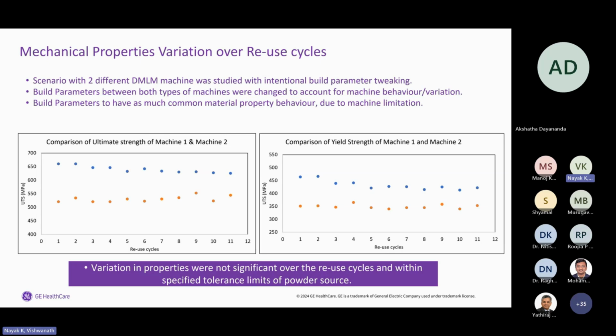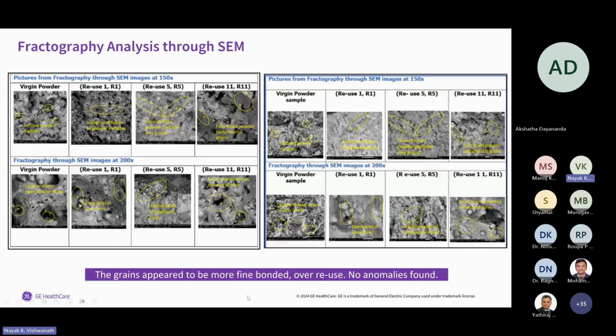So we see that variation is not significant within the reuse cycle, and it was well within the specified tolerance of the powder source. We also perform fractography, and through SEM analysis, we figure out how the material bonding happens for virgin powder with reuse 1, reuse 2, and many different cycles of the reuse.